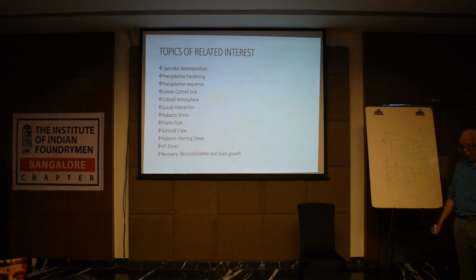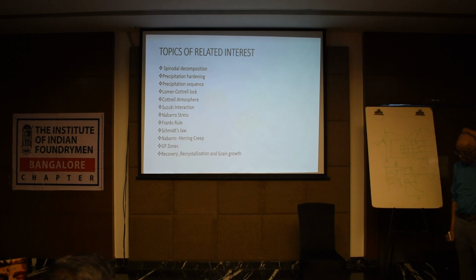So what, you have a coherency strain field. But the coherency strain field impedes dislocation motion. Dislocations in crystals are edge, screw or mixed. The dislocation has a strain field. That strain field interacts with the coherency strain field and forms a repulsive force, by the Peach-Koehler equation, and they try to push the dislocation apart. You need a higher applied shear stress to make the dislocations cut the particle, shear the particle, or loop around it. That is precipitation hardening.